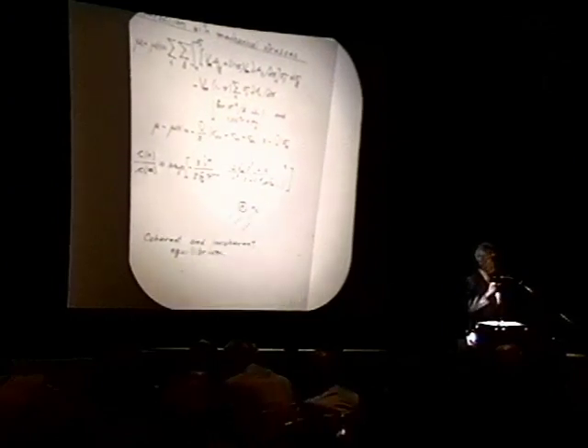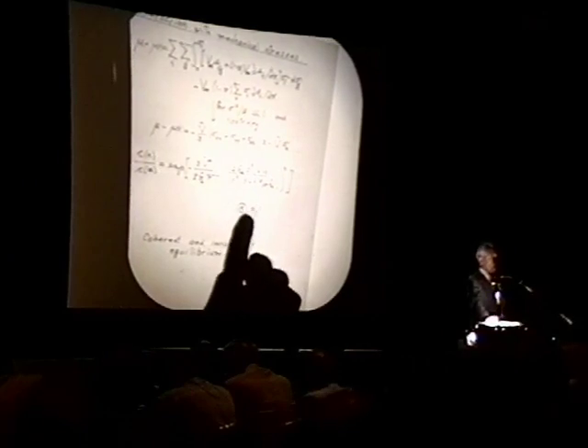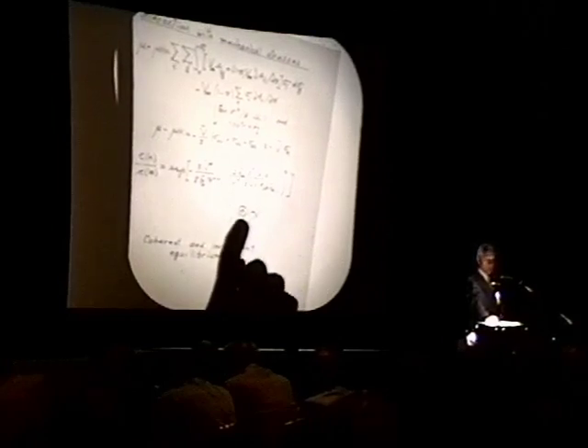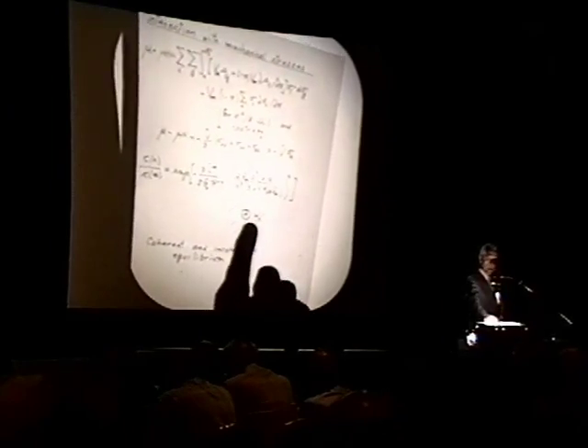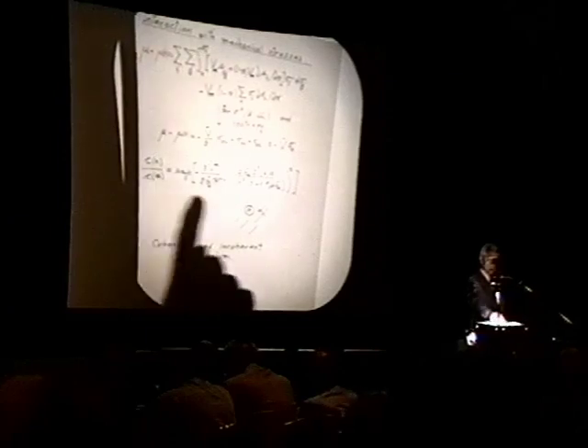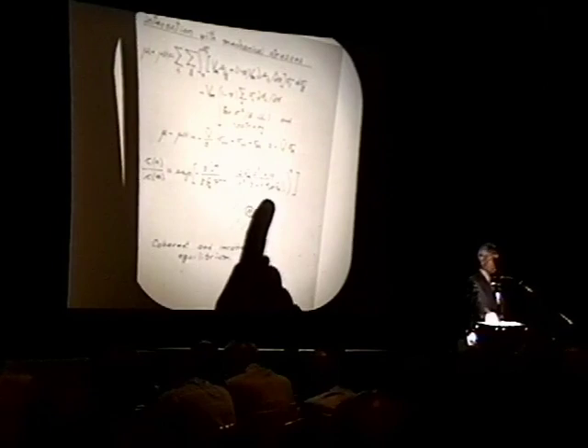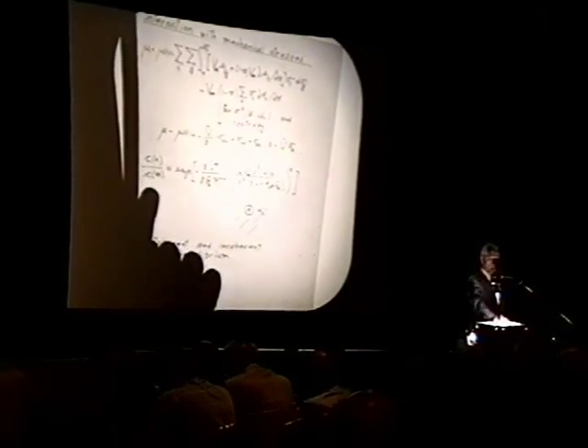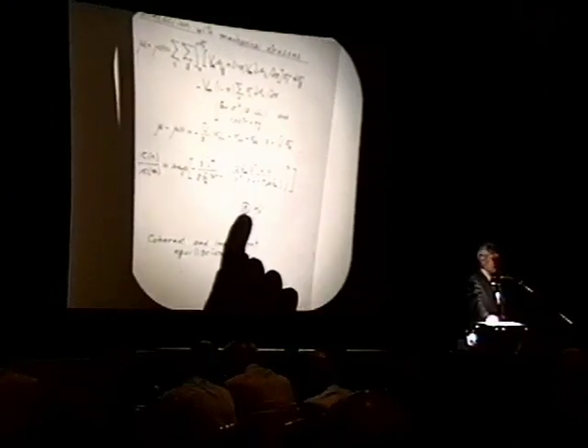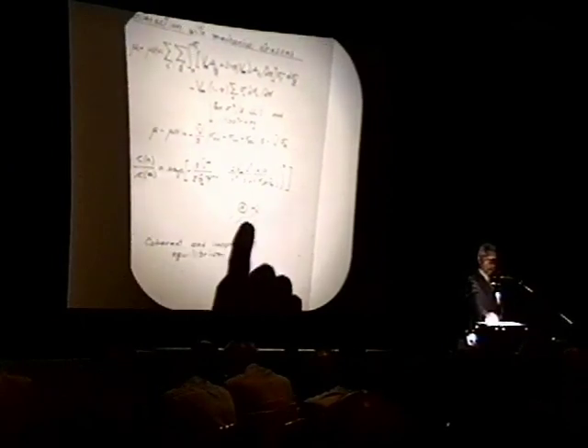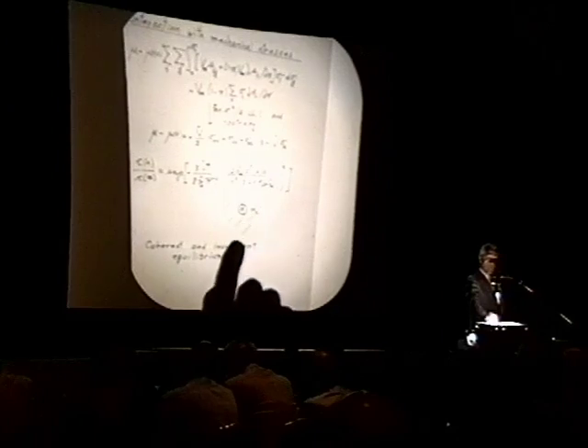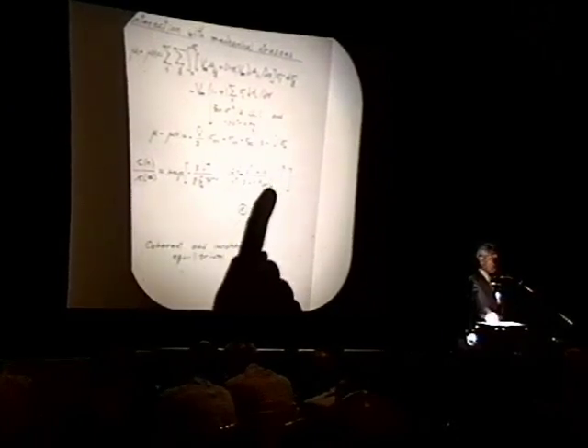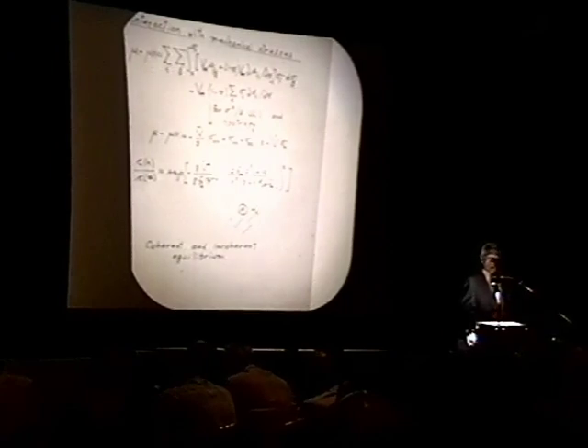In that situation, now I'll make one more reduction. Not for the case of beta phase palladium, because that's really a solid solution, but rather if this were a stoichiometric hydride, such as TiH2, which has a very narrow range of composition, then one can express the spatial variation of concentration of hydrogen in the matrix out here by this sort of expression. The overall concentration at infinity, which is to say far away from the elastic disturbance over here, is raised by the fact that there is hydrostatic pressure upon beta. But there's also a spatial variation, which is given by this expression. Whenever you have an inhomogeneous stress situation in the body, you will have an inhomogeneous concentration distribution in the body at equilibrium, by constant chemical potential everywhere in the system.